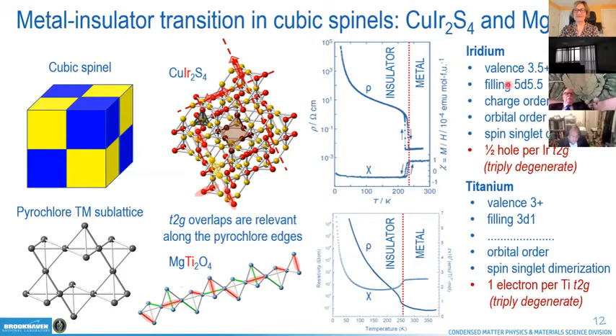So in the iridium case, the valence is 3.5 plus. That appears to be non-trivial, and it originates from the 1 plus valence state of copper. The filling is d5.5. The system exhibits at low temperature charge ordering, orbital ordering, and spin singlet dimerization. And non-trivially, it has half a hole per iridium t2g state, which in the high temperature cubic regime is triply degenerate.